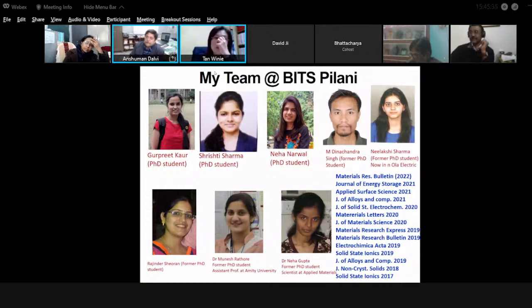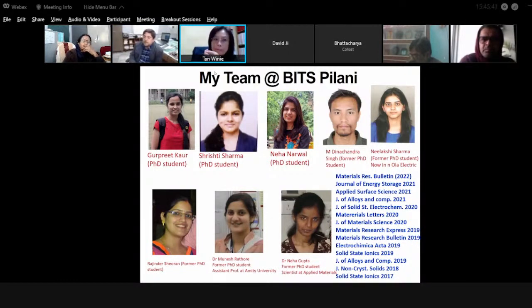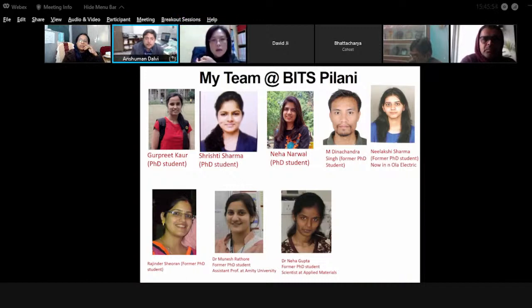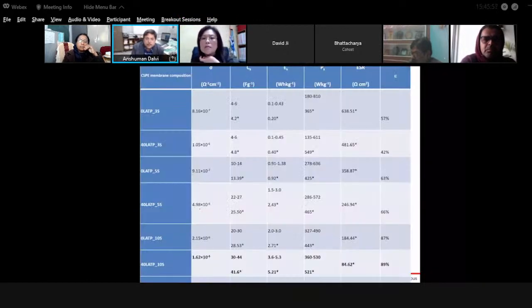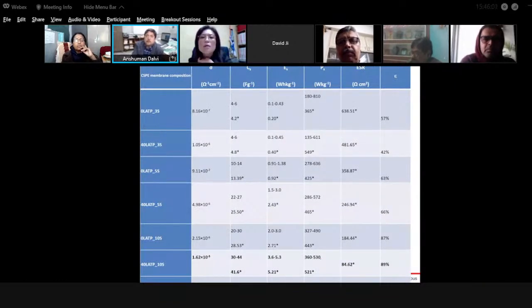So Prof, in your lab the highest conductivity achieved is about 10 to the power -4. Okay. True. And you fabricate the EDLC. So what is the power density of the cell? Power density I have reported in this one. If we see the highest one, it's about 530 watt per kilogram kind of power, which is of course with low energy density, but this is the power density in solid state.